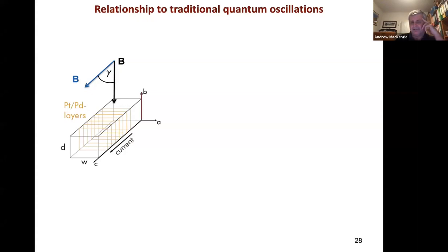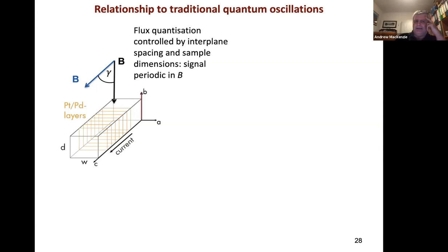He said, okay, you've got this oscillation when the field's in the plane, but you haven't told us anything about what happens as you rotate the field away from the plane to go along the C-axis. So we did that. And what we realized is that when you think about it in the right way, as I just told you, the flux quantization in the in-plane orientation of the field is, if you believe my flux argument, geometrically controlled. And so it's controlled by external geometry, which is field independent.